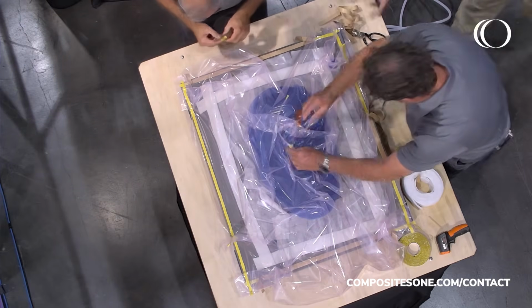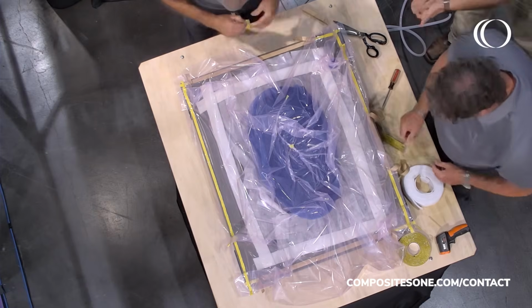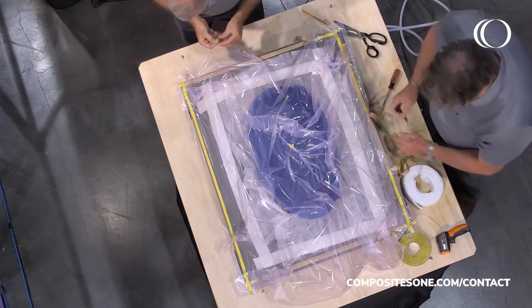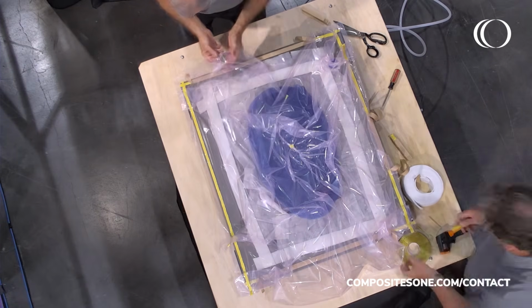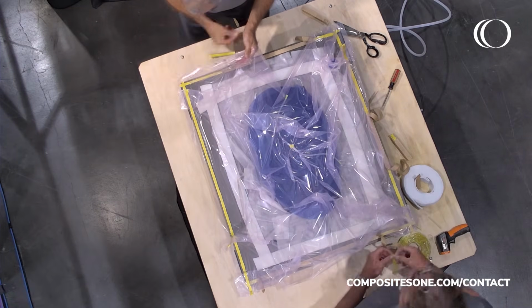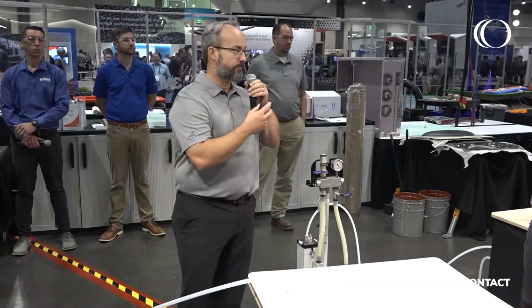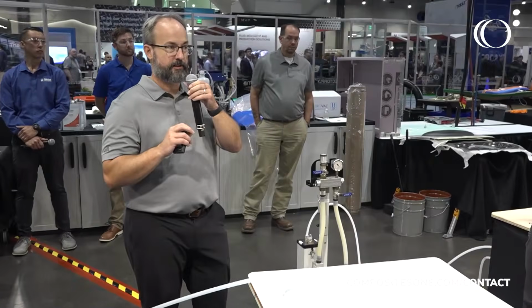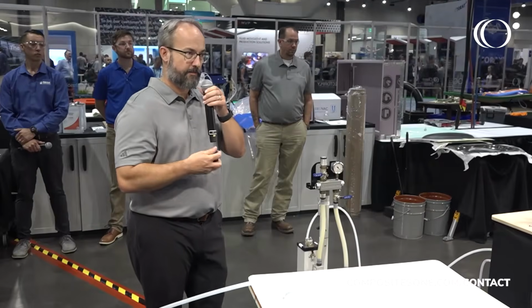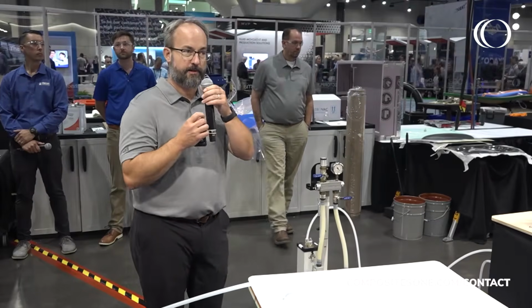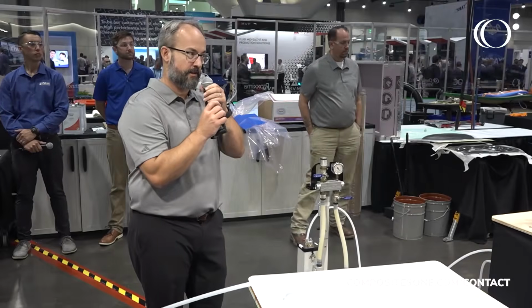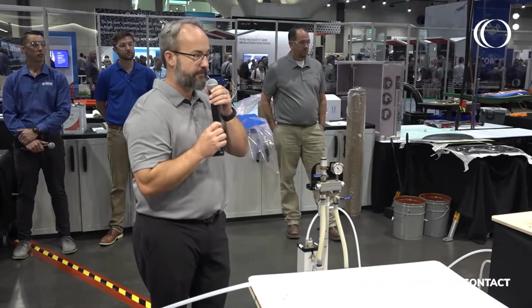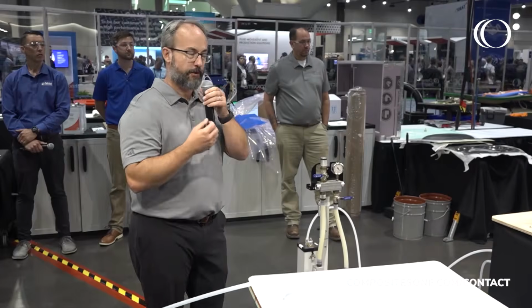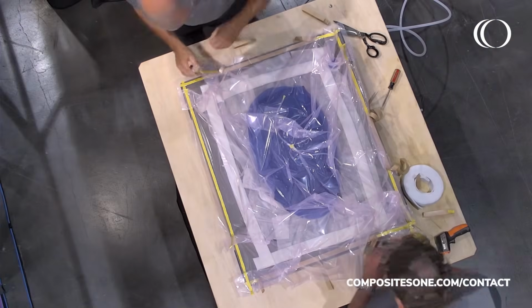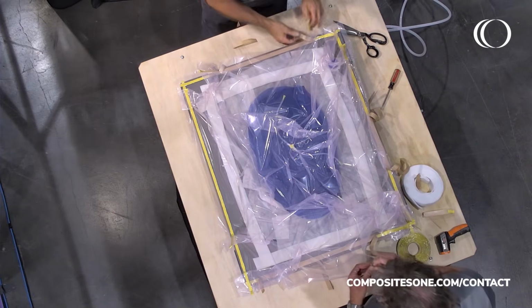There are a number of different strategies in the vacuum infusion process. This is a fairly small part we're doing, but we do have a fairly dense carbon fiber preform. Brandon was telling us that the braided material works well for infusion, but with carbon fiber in general, the actual fiber diameter is very small, so the fiber bundles pack together very tightly. You need a little bit more time for the resin to completely saturate the fiber bundles and completely encapsulate each one of those fibers.